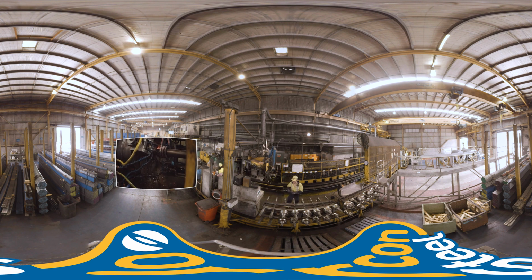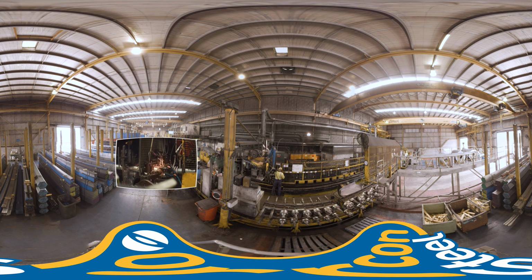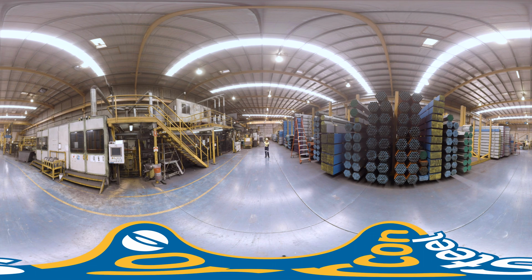The raised weld bead on the outer surface is removed with a scarfing tool. The weld is then water-cooled prior to passing through a eddy current non-destructive test which picks up any weld defects. Once past the non-destructive test, the tube moves to the Turk's head section of the mill. The Turk's head shapes the tube into square or rectangular profiles and straightens the tube to ensure it complies with the Australian standards for shape and size.